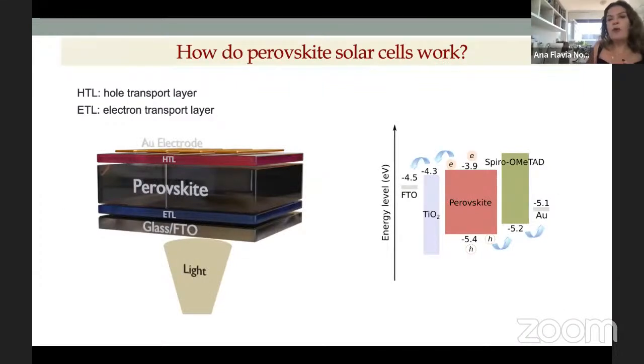So, how do perovskite solar cells work? Taking this configuration specifically, when you have your perovskite, the hole transport layer and the electron transport layer. The electron transport layer can be, for instance, an oxide, and for the hole transport layer, for instance, spiro is the most used hole transport layer in the field. So basically, we have absorption of light, we generate electrons and holes. The electrons are transported through this electron transport layer to the FTO, our transparent substrate, and the holes are then transported to the gold contact on the top of the device. And then we can generate current and voltage. Current times voltage is power.